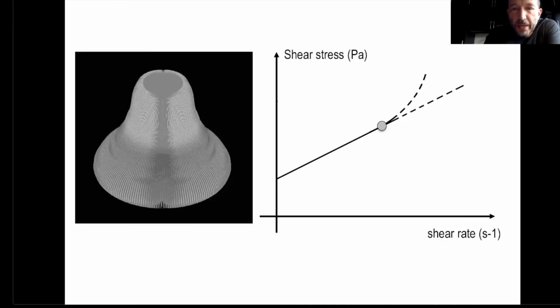So first, an illustration of this relation, of a famous test that is really representative of the first attempts to measure rheology for cement-based materials, slump or slump flow. So what we have is a material in a cone, and then suddenly we lift the cone and the material flows. It flows because the stress induced by gravity is higher than the yield stress of the material.